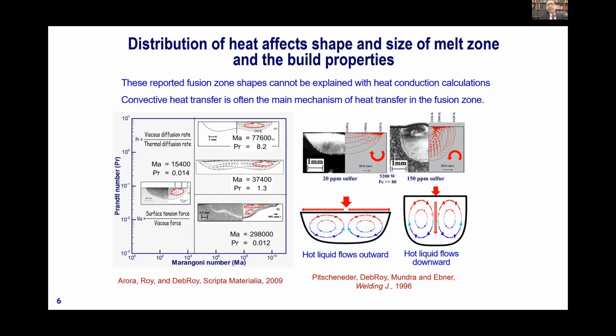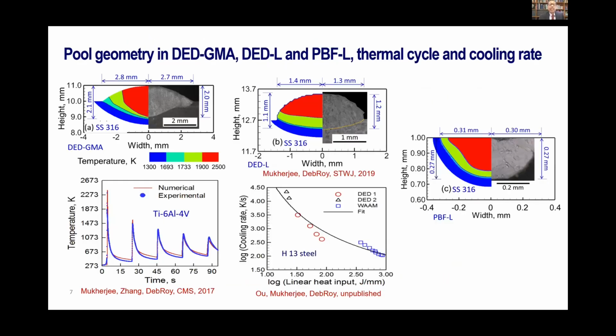And practical application of those is that almost all metallic components have small quantities of oxygen, sulfur, selenium, tellurium, and other minor elements that love to go to the surface of any melt, and they affect the direction of surface tension driven flow. So when we consider those, having about 150 parts per million of sulfur will give us a deep and narrow pool, and having smaller amounts of sulfur will give us a wide and shallow pool. So shape and size of the pool is very important for additive manufacturing as well as for welding. So we can compute those.